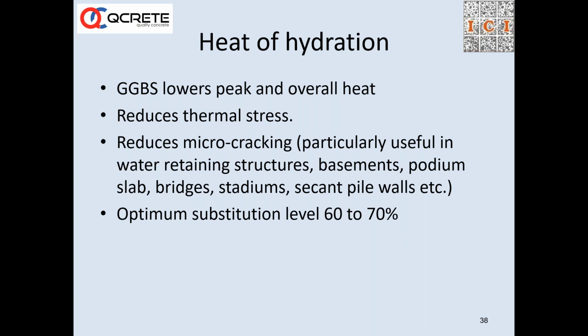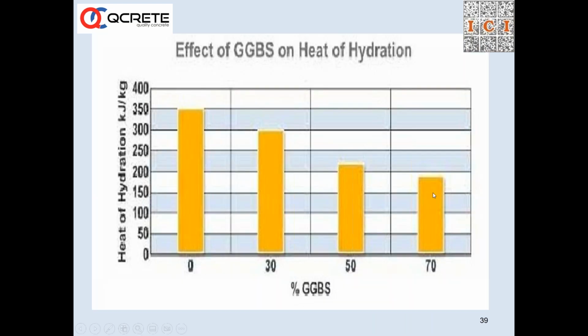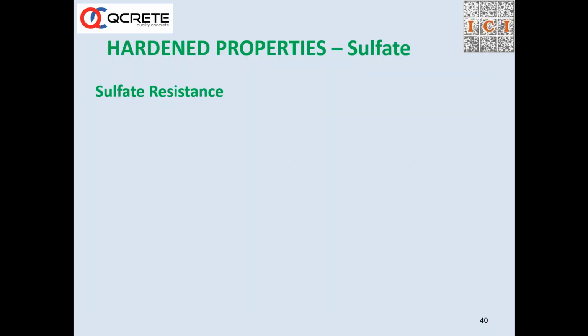5%. So if we use very less amount of this material just for the sake of use, it will not enhance the performance. And on the other hand, if there is a problem with cement itself, a quality problem with cement, it adds to the problems actually. So it doesn't give any result if you are adding at a very low dosage. So we need to add approximately 35 to 50% if you are trying to get good performance. I'm talking about GGBS. So in terms of heat of hydration, when you are having 70% or 50% GGBS, there is a tremendous reduction in the heat generated, which will help in containing the total heat generated in the initial stages and then enhancing the durability eventually.